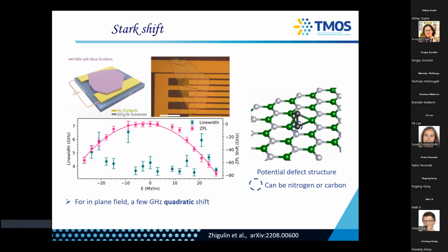Now, it also corroborates well with the two carbon defects, because the 2 carbon defects are in-plane defects, and that's known. So the 4.1 eV is in plane. And so if you break the bond and there is a carbon that can, one will go up and one will go down and will reconnect, then it is in principle a possible configuration. Of course, getting nitrogens is equally easy because it's a boron nitride lattice. So different probabilities. The only thing that we are pretty much locked in on is the symmetry. So on the symmetry, we're very confident. On the crystallographic data, exactly, not so much. So still a little bit of work to do.